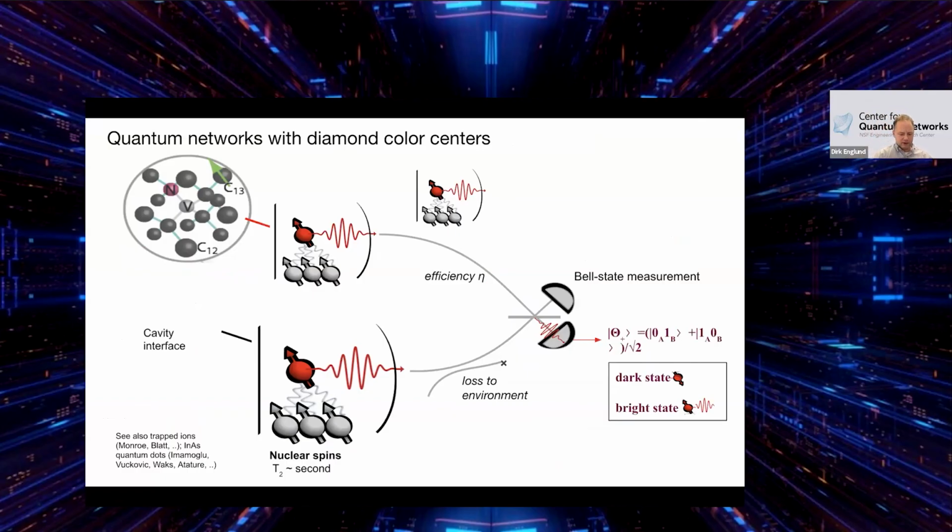What I'm showing you here is one type of color center. This is a nitrogen vacancy center. So you have diamond, a carbon lattice. You pluck out two of the atoms and you replace one of the holes with a nitrogen atom. The nitrogen atom here is small enough that it will select one of the two places. It will either sit here or on the other side. And this asymmetry of the inversion properties of the nitrogen vacancy center, we'll see, is sort of a problem.